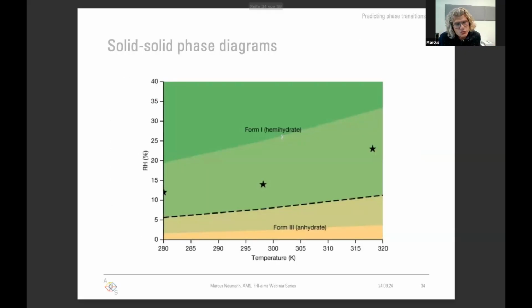We can also do solid-solid phase diagrams, so stability regions as a function of temperature and relative humidity. Here again, for the hemihydrate-anhydrate case, the dashed line would be the predicted coexistence curve, and the shaded regions around it, that would be the 1 sigma error interval. And the stars, those are the experimentally observed coexistence conditions.